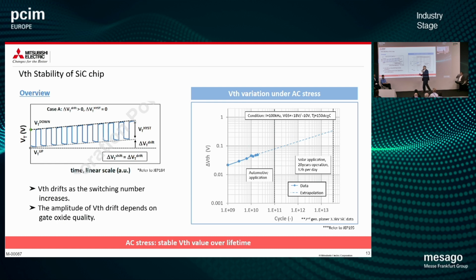Problem? Maybe no problem, because if we take a look at the Mitsubishi Electric result, we're talking here about cycling, the number of cycles, and this is the threshold voltage shift. If we start here, this is an automotive board according to JEDEC, and this is a board for renewable energy for 20 years lifetime, operating 12 hours per day. We see a shift of approximately 0.3 volt within 20 years, and for automotive the shift is below 0.1 volt. Academia talks about a 2 volt or even 3 volt shift within 20 years, but the real data shows just 0.3 volt. The message is: please sleep well, yeah? Within the next 20 years, threshold voltage will not increase so significantly, within 1 volt or within 0.5 volt.